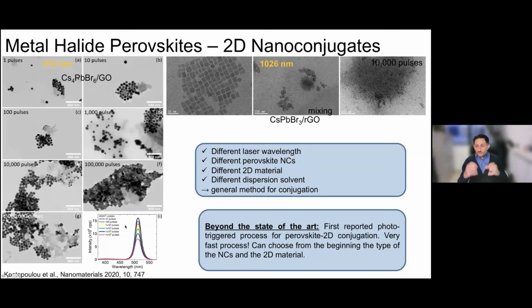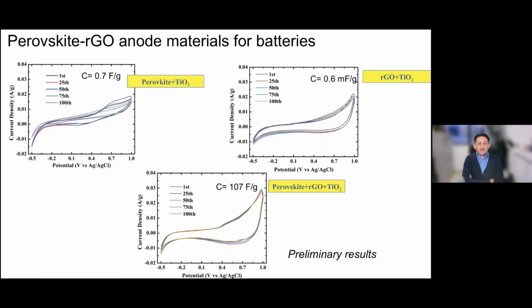We can see the conjugation of the particles with the flakes through the corresponding photoluminescence quenching due to this conjugation. This is the result for this phase with the graphene oxide, but we have also managed, with this three-dimensional phase, to conjugate these nanocubes with the graphene oxide flakes. And of course, here you can play with wavelength, the type of perovskite nanocrystals, the 2D material, and the solvents. So this is a general method of conjugation. These are the first preliminary results, and we have a lot of work to do in order to prove that this is a nice concept for the preparation of conjugated perovskite two-dimensional materials, anode materials for batteries.